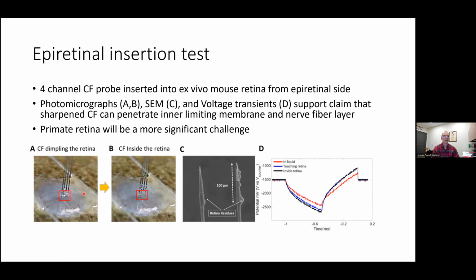Now, will that occur if we have 100 carbon fibers in an array pushing into the retina? I suspect that over time, it will insert into the retina, but will it do so in a stable way that doesn't result in too much damage? And that's to be determined. In primate retina, it will be a more significant challenge because the nerve fiber layer is thicker and the retinal ganglion cell layer, especially around the fovea, has a non-uniform shape, as you most know. So penetrating this array in that region will be a more significant challenge, but this is a good start.